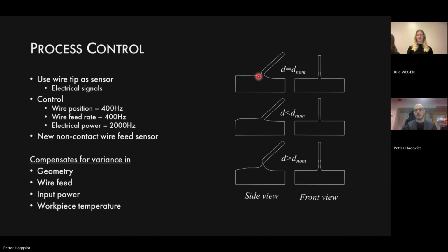So how do we maintain this top situation? Well, as I mentioned, we use the wire tip as a sensor, and the electrical current that goes through the wire, we measure very accurately and quickly. By measuring how the resistance of the melt pool changes, we can tell the difference between these three cases. And what we do is say, okay, we want it to look like this. So we lock in this resistance and we ask our controllers to maintain it by moving the wire up and down, by changing the wire feed rate, and by adjusting the electrical power.